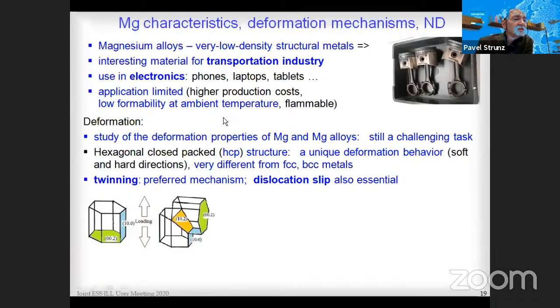Application is, however, limited. One of the reasons is low formability at ambient temperature, and therefore the study of deformation properties of magnesium and its alloys is very important. It is, however, still a challenging task because magnesium has unique deformation behavior, very different from BCC or FCC metals, as it has an HCP structure. So the preferred mechanism for deformation is twinning, but there is also very important dislocation slip.